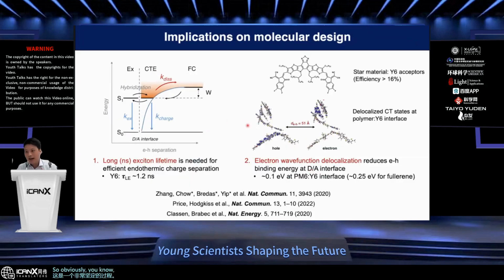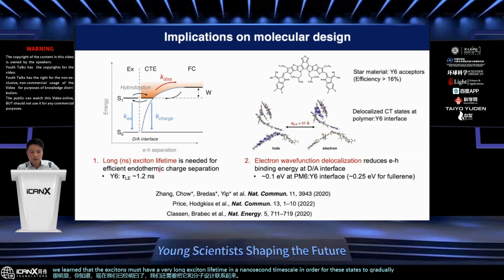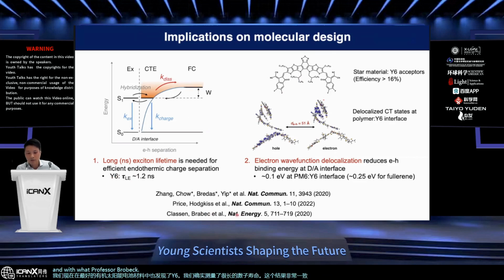Now we understand what's going on, we also need to relate it back to the molecular design. Because of this process, we learned that the excitons must have a very long lifetime, in a nanosecond timescale, in order for these states to gradually separate. This is also what we found in the best organic solar cell material right now, known as Y6, and we do indeed measure a very long exciton lifetime. This result is very much consistent with what Professor Brabec has found and published roughly at the same time.